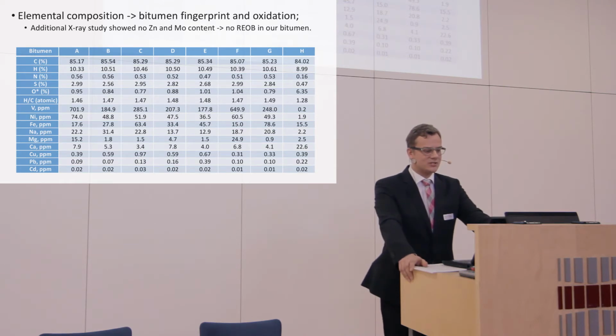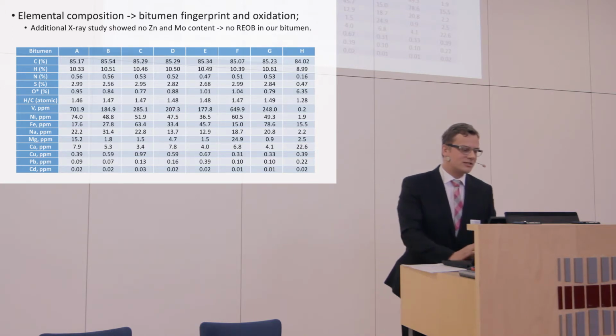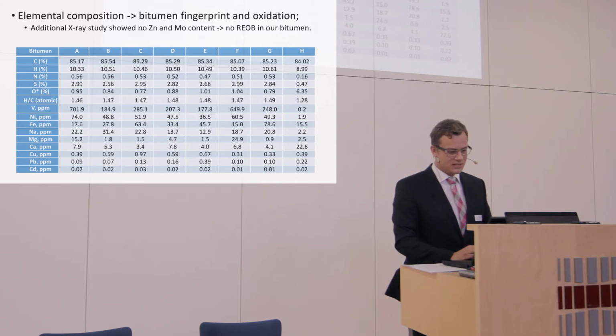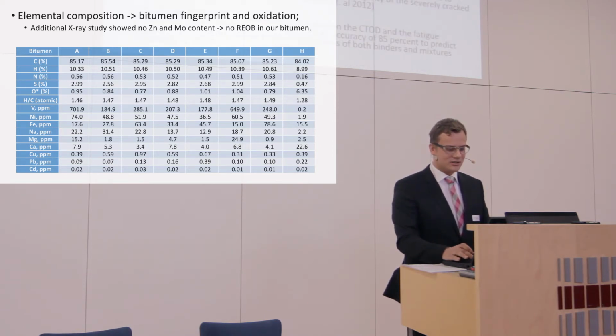We made an elemental composition analysis. There we can see the bitumen fingerprint, and we can assume a little bit about how fast or how slow is the oxidation in bitumen. Also, additional X-ray studies showed that no zinc or molybdenum content was in our bitumen, so no waste engine oils at the moment inside it. So these physical hardening figures, as you can see here, are not because of waste oil. They have to be from some other source.